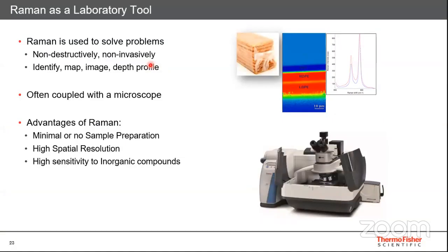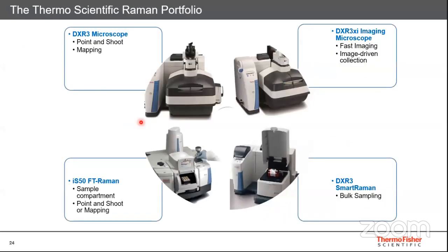Raman spectroscopy, as I said, is a non-invasive technique. You can couple the Raman with a microscope. No sample preparation. Another important advantage of Raman is that it has very high spatial resolution. You can go up to 0.5 microns using Raman, and it has high sensitivity to inorganic compounds. So at Thermo Fisher, we offer different types of Raman spectrometers. One is the DXR3 Raman microscope, which has the capability of point and shoot as well as mapping, so you can have a mapping of your sample. The DXR3 imaging microscope is the same microscope where you can do the analysis faster.